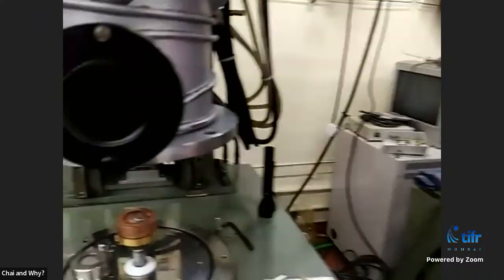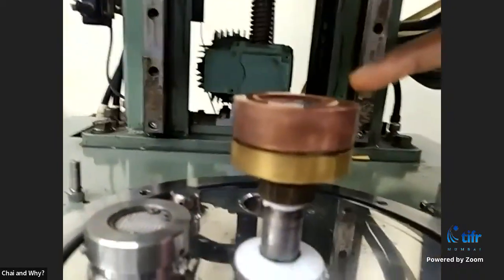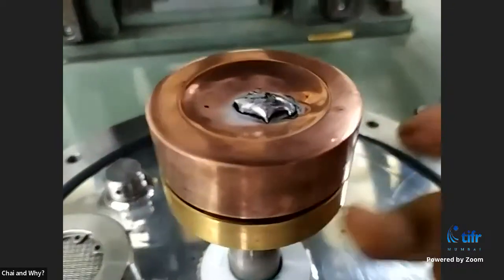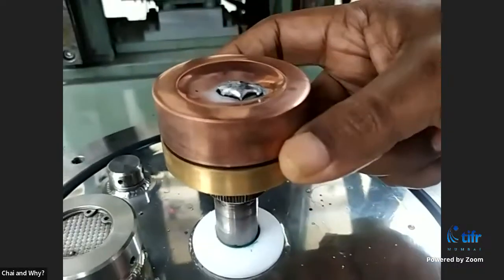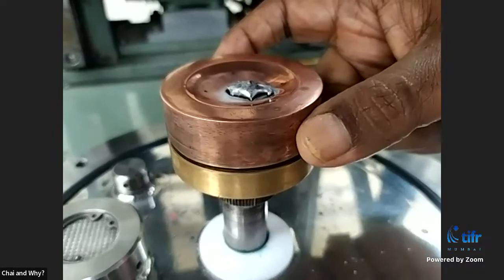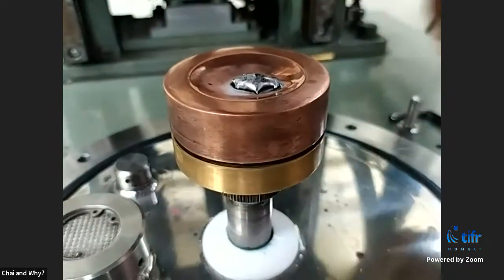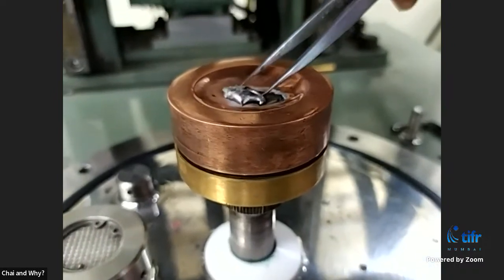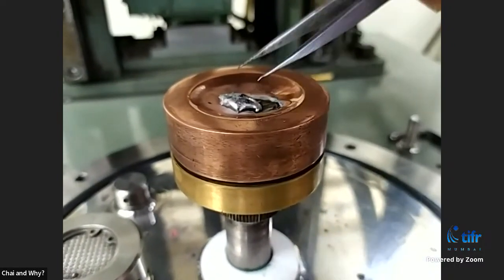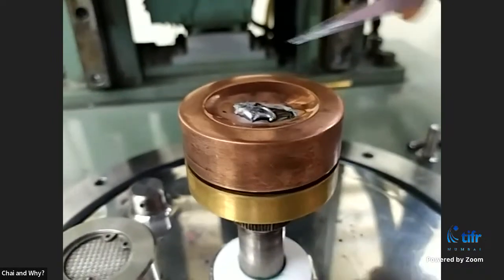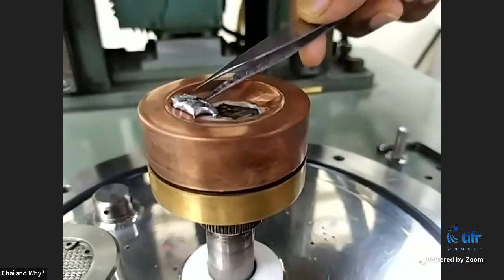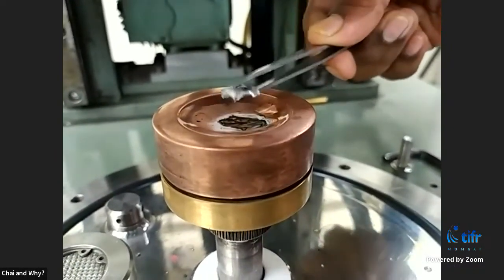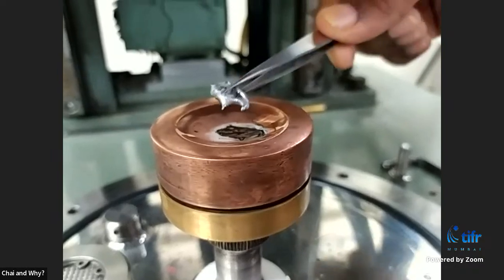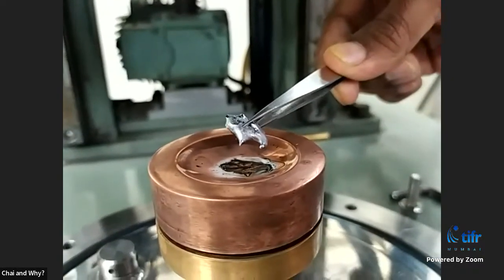And this is one of its sophisticated furnaces of Czochralski method. So you can see that. Right now you have seen that this is the alloy that we have made as of now. This is the copper hearth. The water comes inside this tube up to this copper hearth. Because of the thermal conductivity of copper, the entire heat is taken by this copper. And we had these cerium, rhenium, and silicon, which are kept as individual metals. And as I told you, those have different melting points, the rhenium being the highest with 3200 degrees centigrade. And we have melted this sample, and this is how the alloy looks like. So right now, this does not have a proper shape.